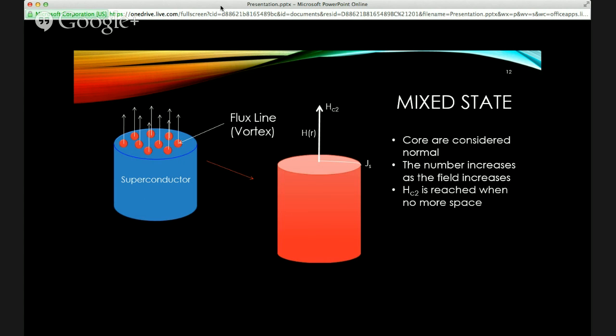So it's kind of difficult to see. I tried to curve it as much as I could, but in this blown up flux line you see where the core itself is normal, and the actual field is a function of the radius of these flux lines. And what you have on the outside is a shielding current. And so you have two different types of current. You have a shielding current, which encircles this vortex flux line. And then you have a transport current, which is separate.